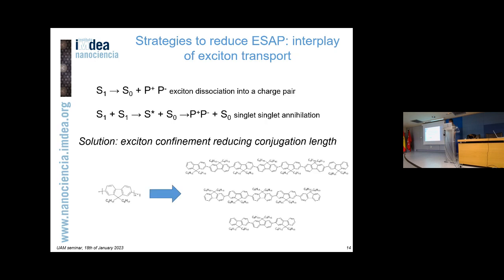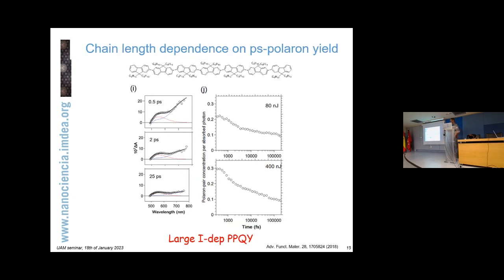If you think about these two processes, in both of them you need diffusion - the exciton has to diffuse in order to dissociate. So one way to avoid this problem would be to reduce conjugation length. We tried to verify this hypothesis by looking at three different oligomers of this polymer with 3, 5, and 7 units, and performed the same sort of experiment.